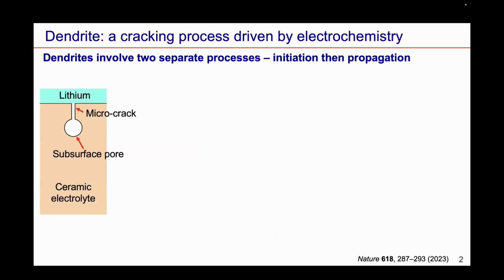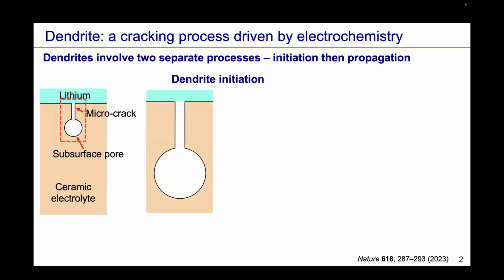Our group recently proved that dendrite growth involves two separate processes, dendrite initiation and then propagation. The dendrite initiation is closely related to the microstructure of the electrolyte, especially the presence of pores. Many of these subsurface pores can be connected to the exterior of the electrolyte through micro-cracks. When we charge the battery, lithium is plated onto the lithium metal anode and preferentially deposits along this micro-crack until it fills a pore.